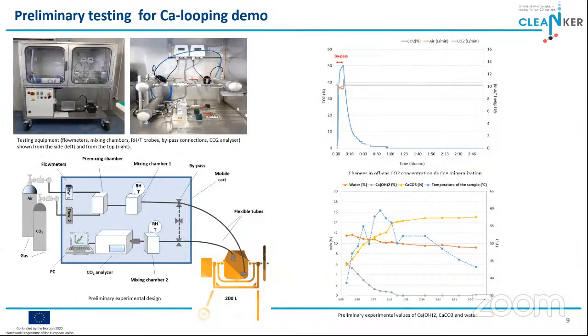Solid samples were collected after every 10 and 30 minutes and submitted to thermogravimetric analysis for quantification of calcium carbonate as well as portlandite. You can see in the graphs on the right that the results indicate the system saturated after 2 hours, as portlandite became depleted and the calcium carbonate stabilized. From here, it can be said that preliminary testing confirmed that CO2 can be mineralized from a gas mixture by burnt oil shale in the proposed wet conditions.